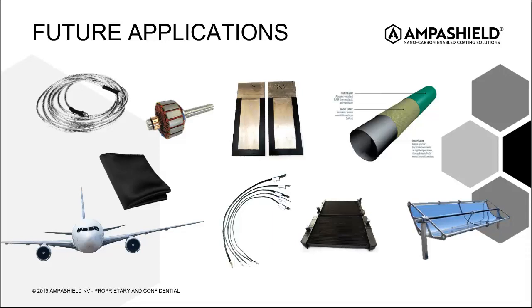We've seen the resistive heating sheet on the left-hand side. We see some cables here, which were coated in Ampashield Thermal. This enabled one producer to reduce the wire size by 1 grade, hence saving an enormous amount of, shall we say, kilograms in the aircraft, basically giving them a longer distance they could fly for the same amount of fuel.